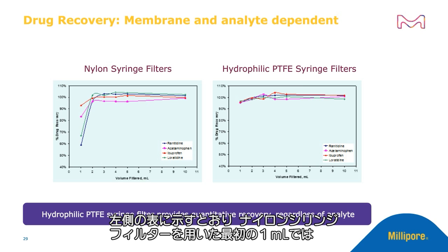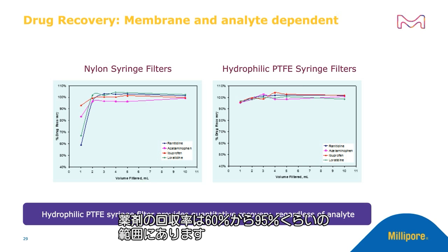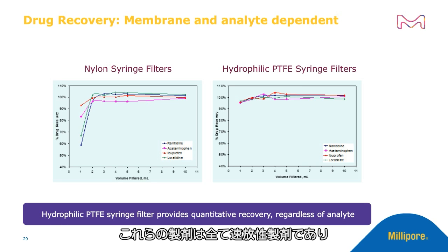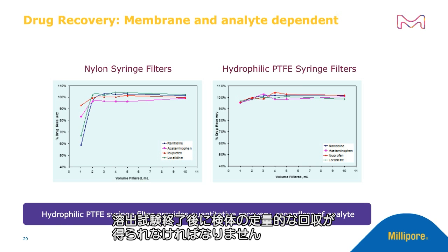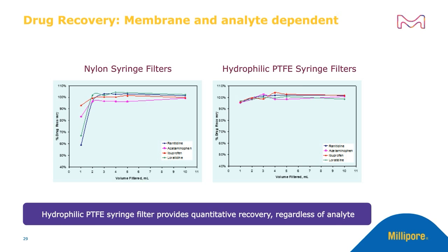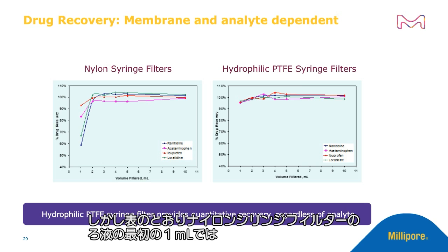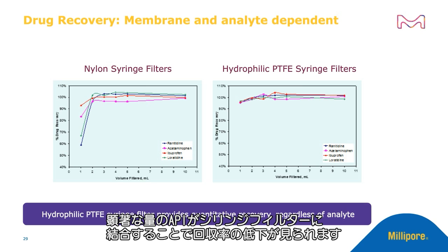As you can clearly see on the left-hand panel, for the first ml of filtrate, using a nylon syringe filter, the drug recovery that is obtained is somewhere in the range of 60 to 95%. All these formulations are immediate release formulations, which means after the dissolution test is completed, quantitative recovery of the analyte should be obtained. But you can see that for nylon syringe filter, for first ml of filtrate, a significant amount of API binds to the syringe filter, leading to low recovery of analyte.